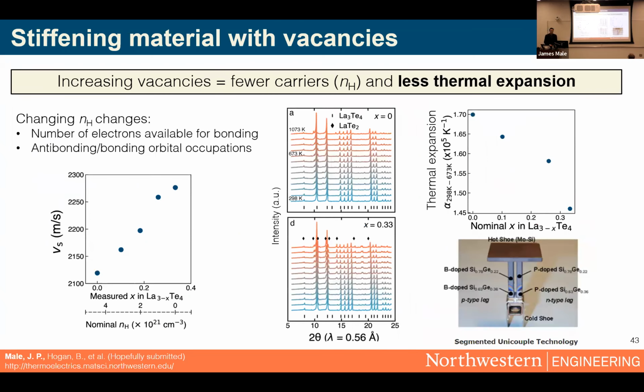There's actually an interesting practical consequence of this in the thermal expansion coefficient. So as you stiffen a material, you would expect the material to expand less with temperature. And from high temperature X-ray diffraction, I found that that is indeed the case. We can actually reduce thermal expansion by adding vacancies. This is actually potentially useful for improving the usefulness of these materials in modules where you need to match thermal expansion coefficients between different parts of the material.